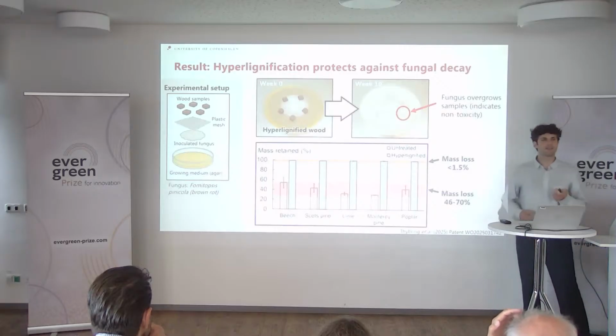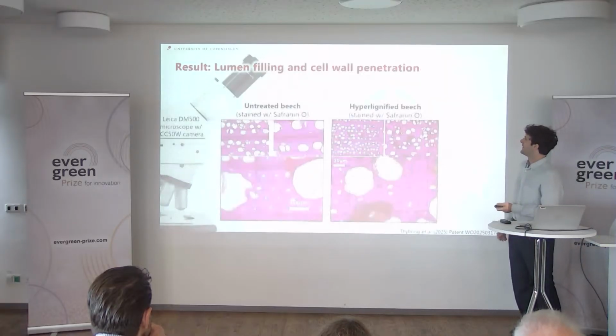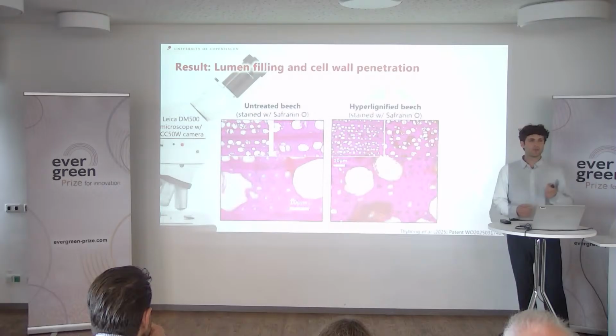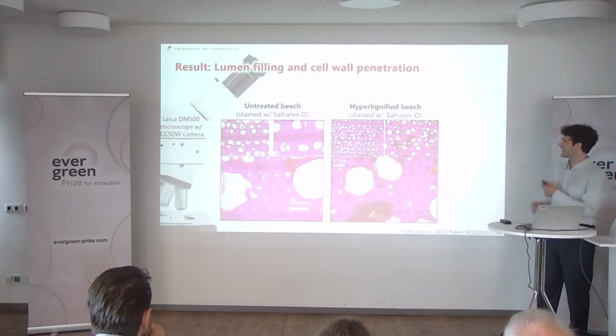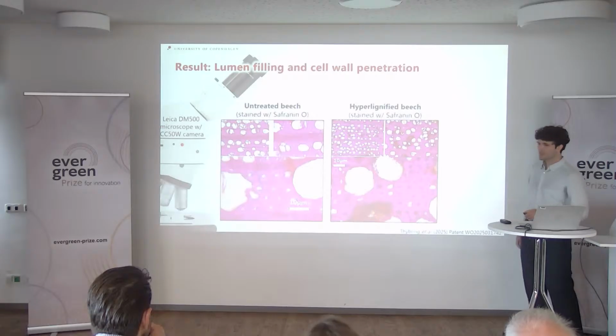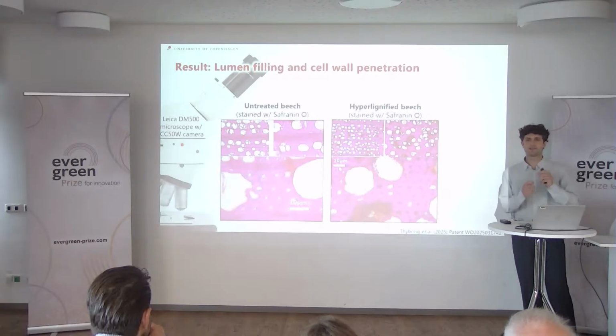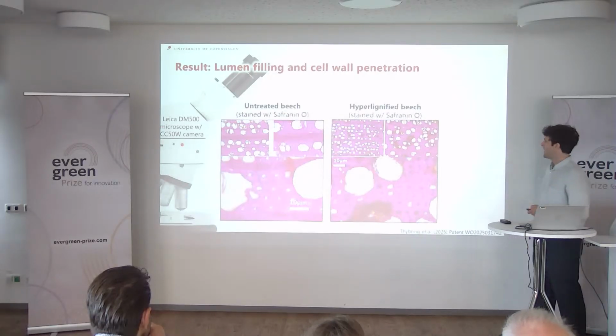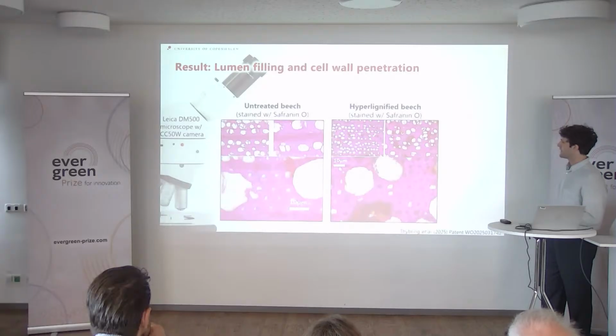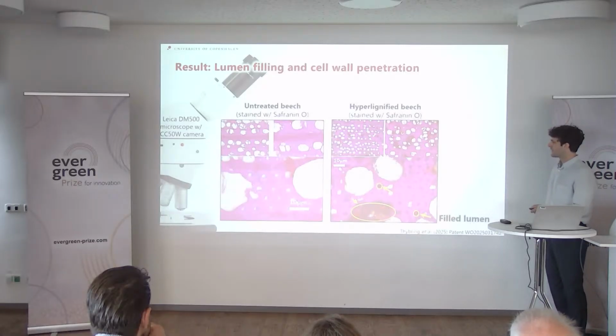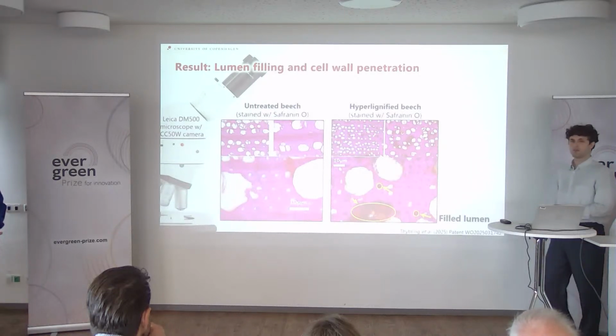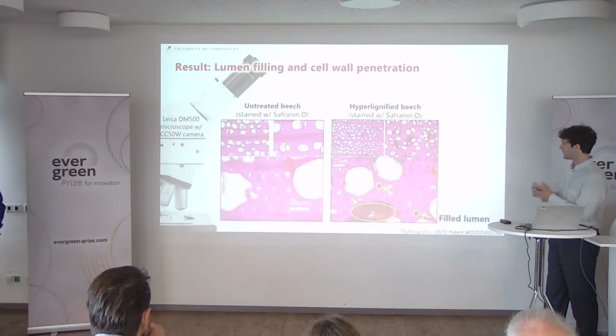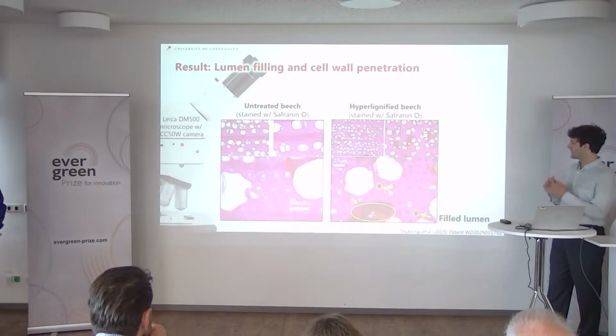How did this work so well? So we literally zoomed in, we took microsections and used a stain, safranin, which targets lignin substructures and makes it look purple under the microscope. And what we saw was quite revealing, because we could see that the lignin impregnates the voids, which are the large vessels and the small ones of the fibers. So the lumen of the fibers and the vessels were impregnated.